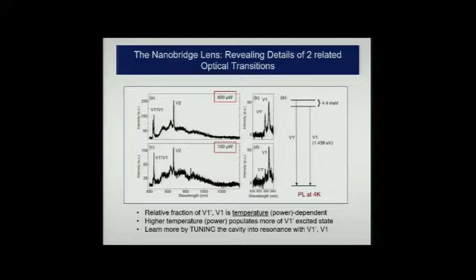If we take this with the fact that we see a higher peak for V1 prime when we have higher incident power in our measurement, here is the thinking we might go through. Higher incident power, higher local temperature, we don't know exactly what it is. Higher local temperature, higher thermal energy, just the Boltzmann statistics suggest that we might have a higher proportion of the transitions making it to the higher energy excited state. So let's look a little bit further.